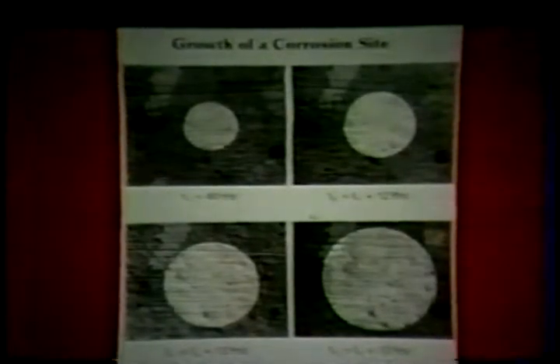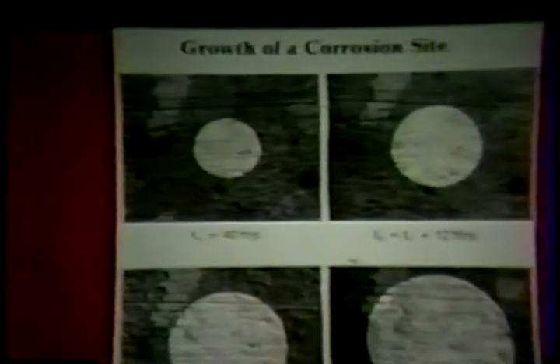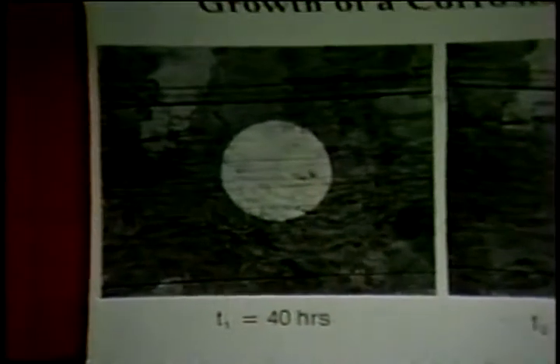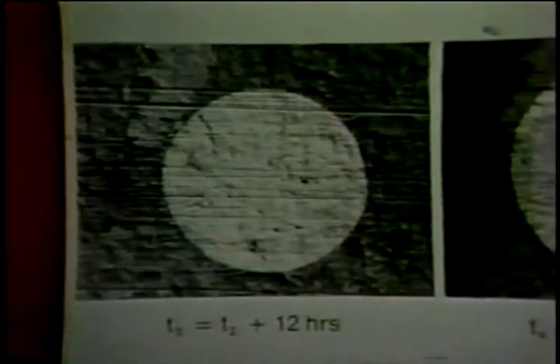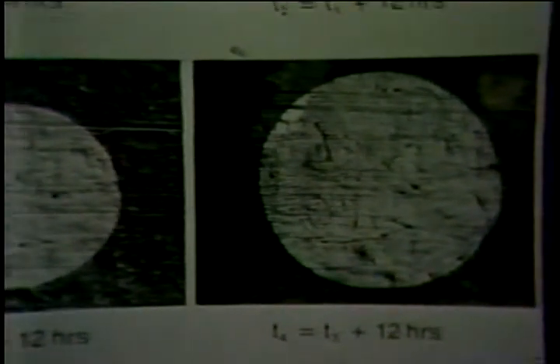We have identified one particular corrosion site as it initiated and photographed it 40 hours later. This is shown in the upper left-hand section. 12 hours later, we see that it has increased its diameter. This is shown in the upper right-hand area. 12 hours after that, it was photographed again, and again 12 hours after that. And in each of these photographs, we see that the diameter has increased in size. We can measure this diameter and obtain an idea of the growth rate of these corrosion sites.